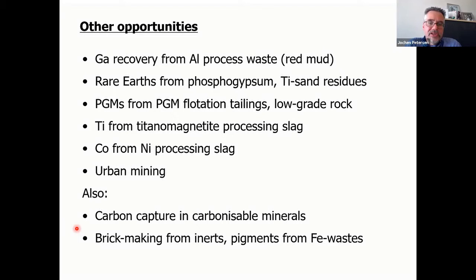PGMs from PGM flotation, tailings or low-grade rock. There is still very little underway in terms of trying to recover additional values from those flotation tailings, because the flotation might be in the order of 80 to 85% efficient, but the remaining 15 to 20% of PGM value, given the tonnages that the PGM industry produces, is still of quite significant value if one can find a suitable way of extracting them.